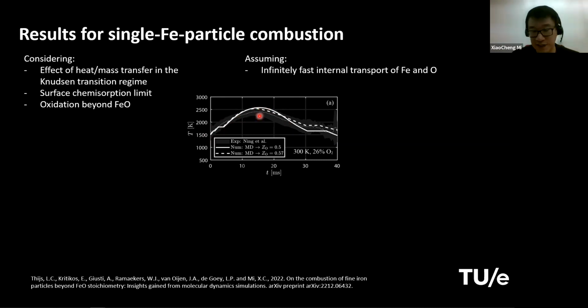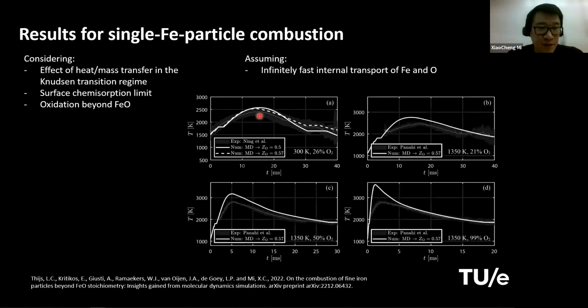Because you have these limitations to slow down the reaction rate, right? But the problem is, if we look at what happens at the higher oxygen concentration or higher environment temperature that are obtained experimentally in this drop tube setup, the match is not as good as for this cold environment, low oxygen concentration. So for this 21% or air at this higher temperature, the overall trend is okay.